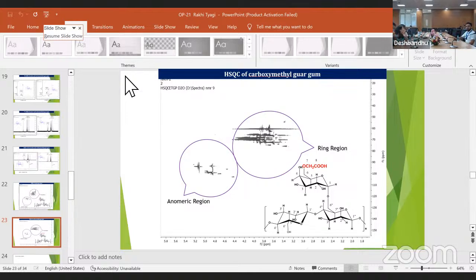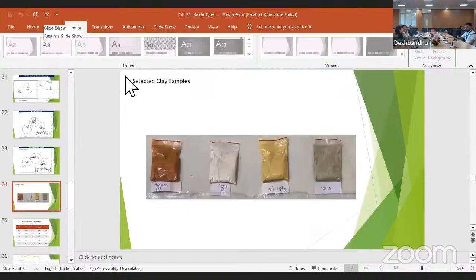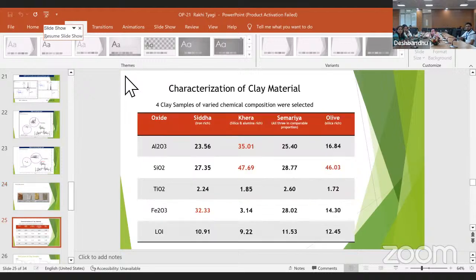These are the selected clay samples. As we can see, the colors of the selected clay samples are very different, which is also reflected in their chemical composition. This is the XRF data for the selected samples. I have marked the major components, which are about 30%. The sample Siddha was rich in iron. The Khera was rich in alumina and silica.